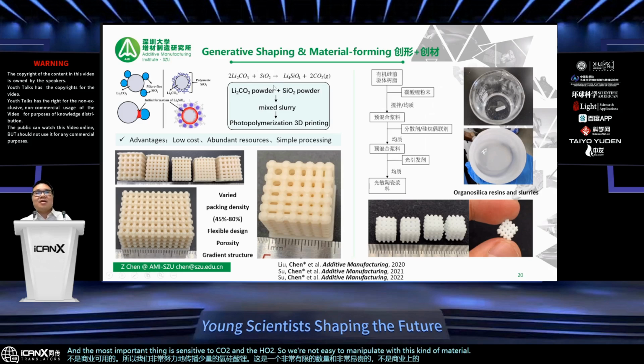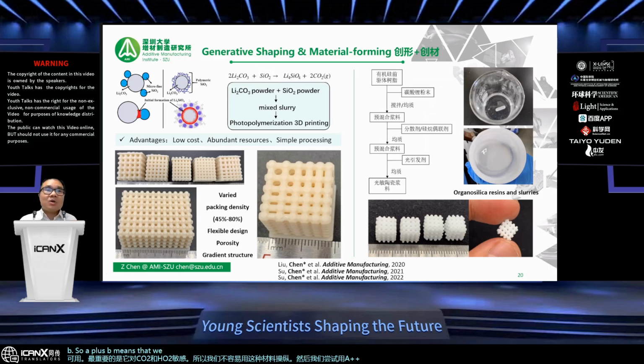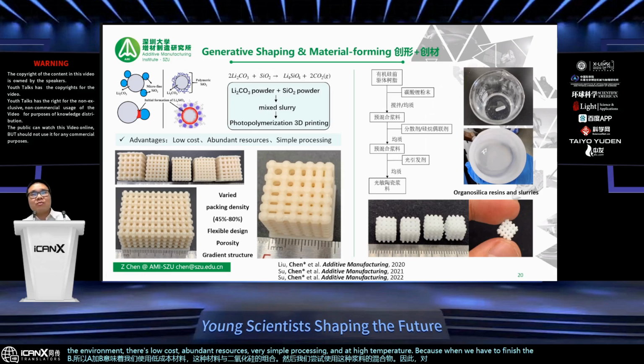So A plus B means that we use low cost material, a combination of this one with silica. Then we try with the mixture of this kind of slurry. So there's no longer sensitivity towards the environment. There's low cost and abundant resources, very simple processing, and at high temperature, because after we finish the slurry, then we do 3D printing.